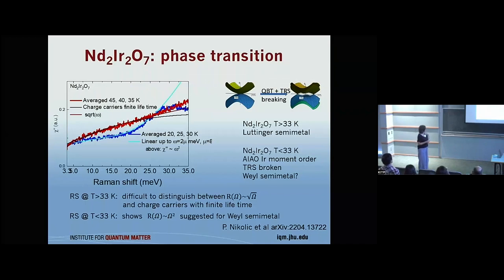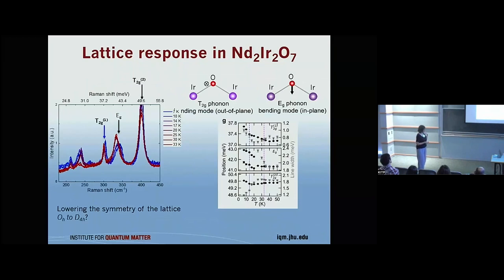So for us it looks like the square root, so this red spectrum, which is a high temperature spectrum, square root of frequency and quadratic band touching is in agreement with what we see. The frequency dependence of the continuum below the transition is very well fit by a quadratic dependence on frequency. So from this experiment, we argued that we actually see the transition from quadratic band touching into Weyl nodes, and it happens on the order of the iridium ordering temperature. Yeah. Okay.